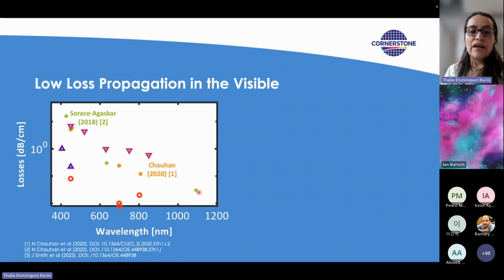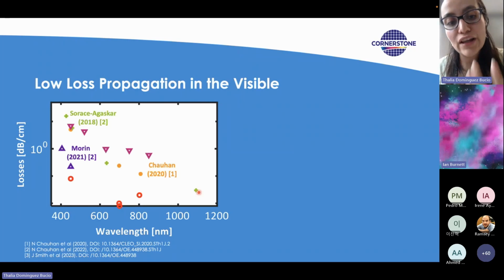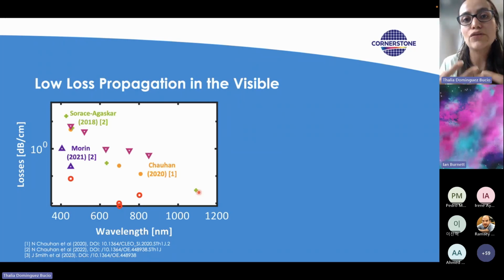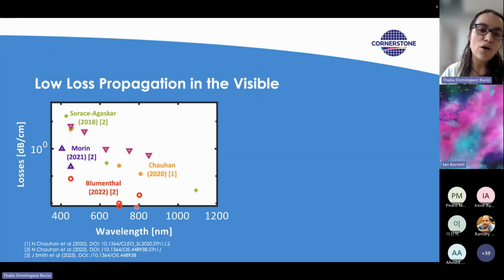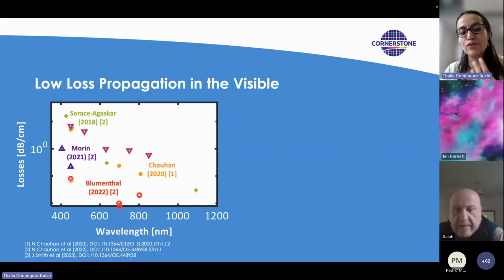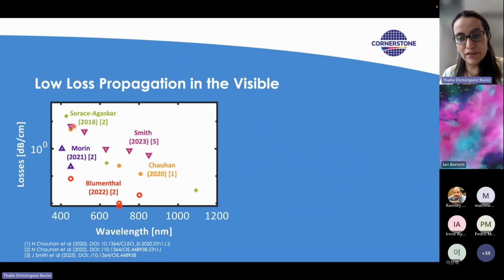However, to reduce the losses that you achieve with these waveguides, what you need to do is go into a low confinement waveguide regime. So if you reduce the thickness of your layer from 100 nanometers down to 20 nanometers, it is possible to reduce the losses to levels below 0.05 dB per centimeter in the whole wavelength range, covering 450 nanometers to, let's say, 900 nanometers. But these are not the standard layers that are available in foundries. If you just talk about foundry fabrication layers, typically they will have losses in the order of 1 dB per centimeter all the way to 6 dB per centimeter.